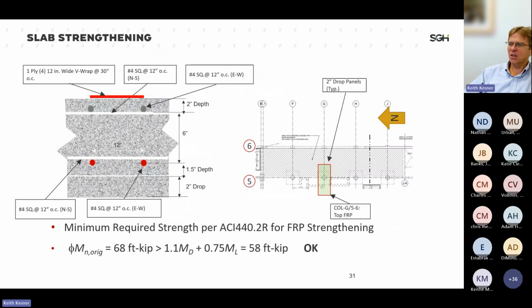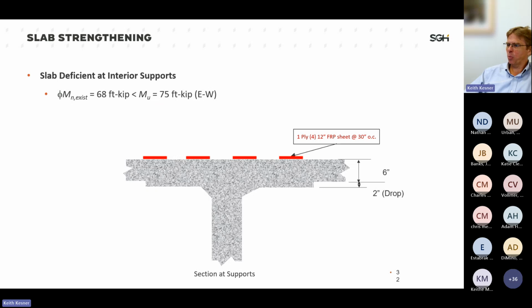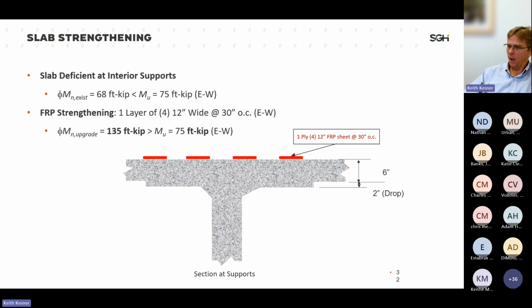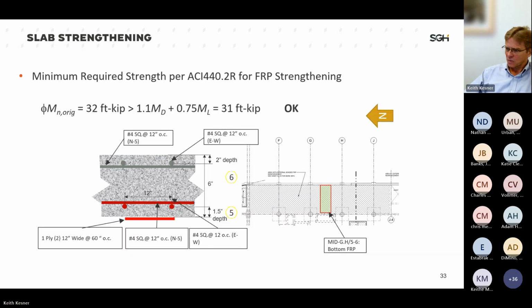Taking a look at different sections, a single ply of the fiber, 30-inch spacing, 12-inch wide strip, adding that onto the existing reinforcing steel on the top side, and we end up with a calculated minimum strength. We check our minimum strength, that was okay. And then at the interior supports, we're adding in one strip with the FRP, spaced 30 inches on center. And then we're determining that the upgraded strength is substantially better than originally designed strength. We could probably get rid of some of that FRP, make that a little bit thinner.